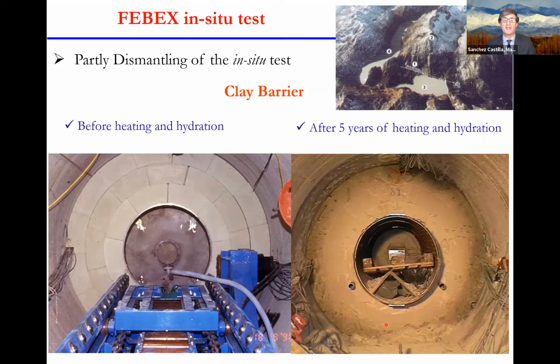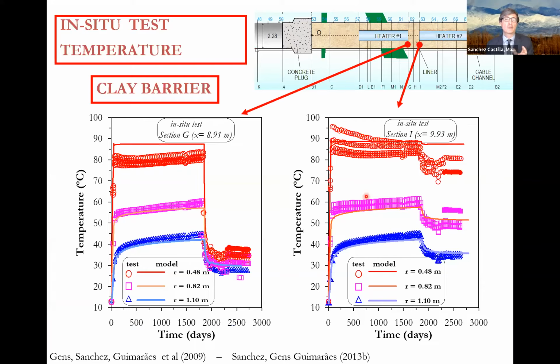And here you have the barrier 5 years after the start of the experiment. You can see that it is more or less homogeneous. All of these gaps were closed, and the barrier is mainly hydrated from the external part of it. We have compared our code, and this was a kind of blind prediction, because Enresa, the company in charge of this experiment, asked us to provide the simulation results at the beginning of the project.